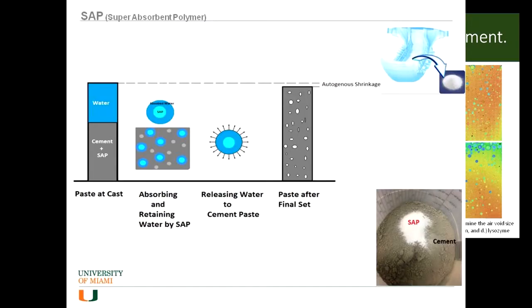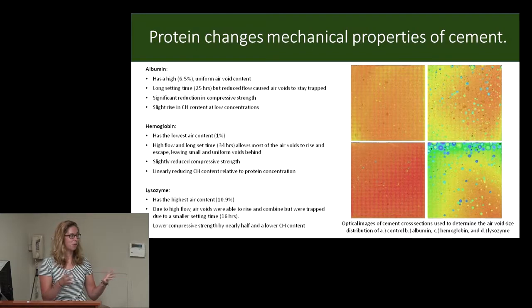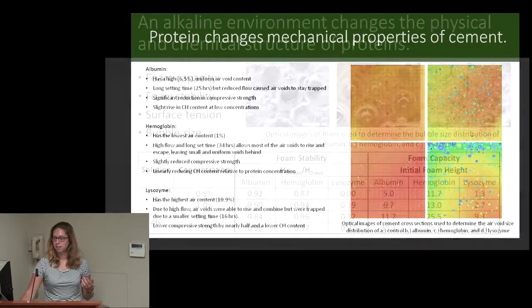Hemoglobin was very similar. It had a very high foaming ability, but a very low air content, because the flowability was so high and the setting time was over 30 hours that all the air was able to escape. Lysozyme, you can see this little middle area where the larger air voids joined together and rose to the top, but were stuck before the setting time allowed them to rise fully to the surface.